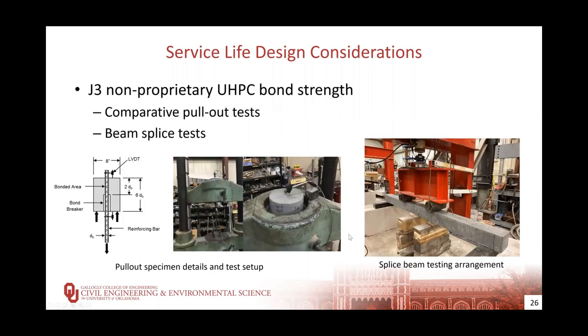In addition to the durability performance of the UHPC material and interface with the conventional concrete, an important consideration for performance of the link slab is the bond between the connecting reinforcing bars and the UHPC. Two series of comparative pullout tests were conducted to examine the effect of steel fiber content on the bond of reinforcing bars cast in the non-proprietary UHPC, and a series of beam splice tests were conducted to obtain more realistic bond stress values for typical configurations.